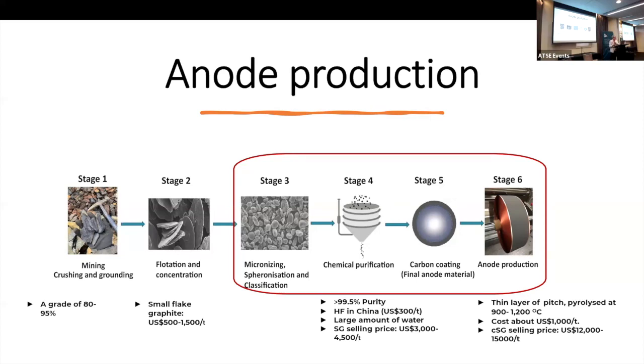There is a great deal of waste from this process. About 60% of waste graphite is produced in terms of fines. And we're looking at applications to use those fines for high-speed applications. This is where you really want to do rapid charging very quickly, because your particle size is very small relative to about 12 microns that you need for these spheronized particles.